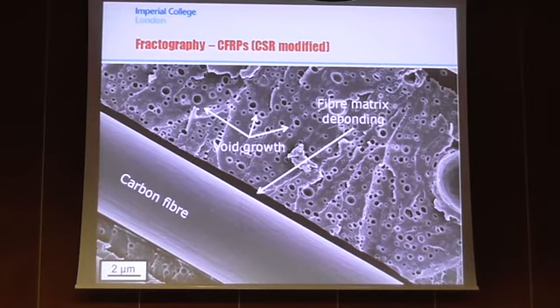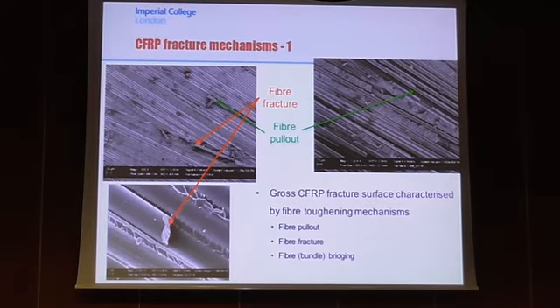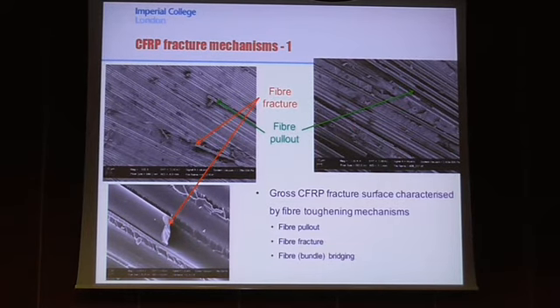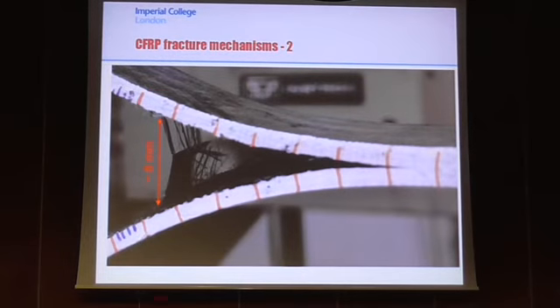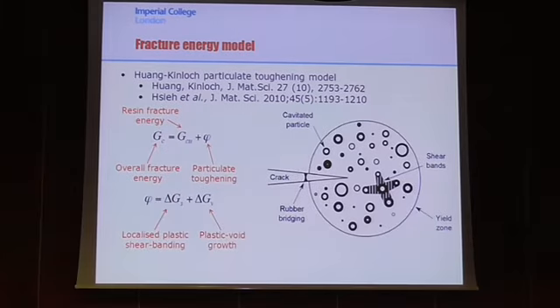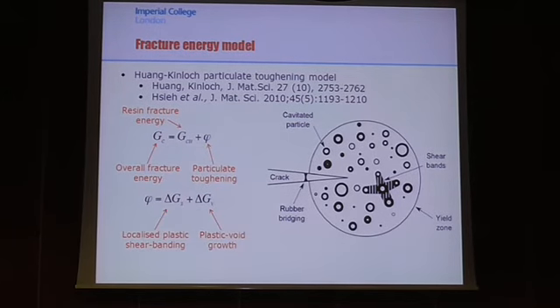In the CSR modified materials, it's much more clear. We can see void growth and cavitation. So this indicates that when we look at this surface, we see the cavitation and void growth, so basically the toughening mechanisms are being induced. And then the fracture mechanisms on a larger scale are dominated by fibre fracture, fibre pull-out, and also fibre bundle bridging. So this is a picture of some of the most excessive fibre bundle bridging that I saw in my tests. And then I'll quickly just go through some fracture energy modelling.